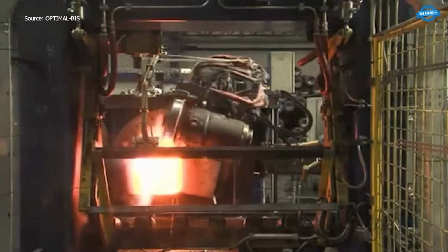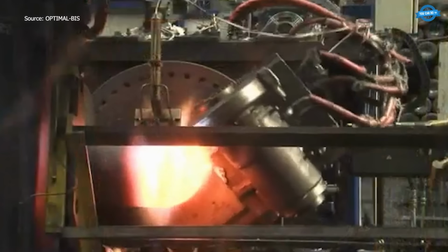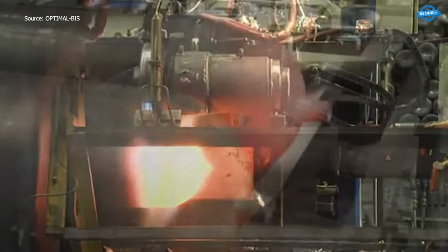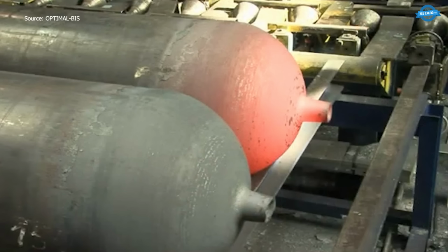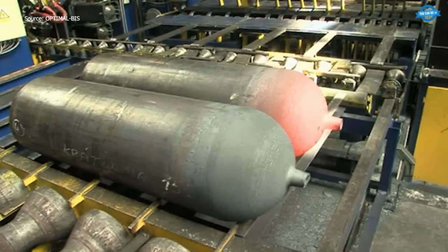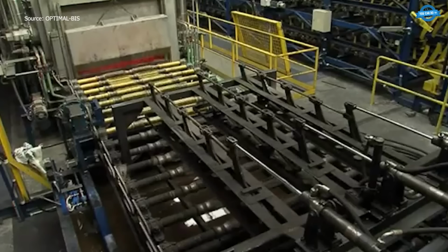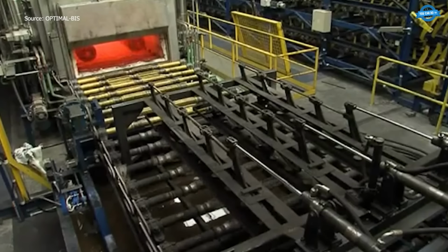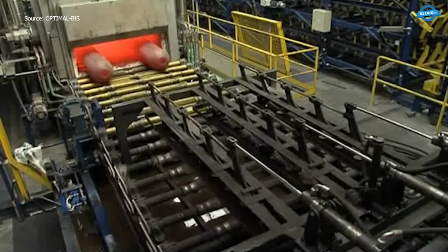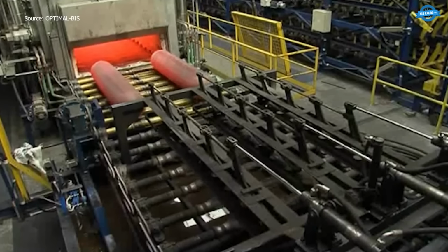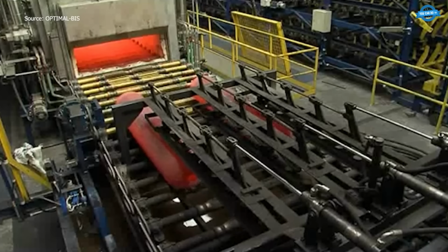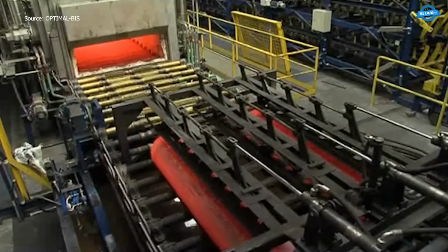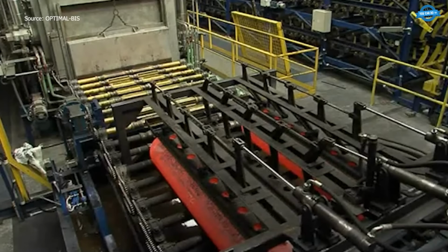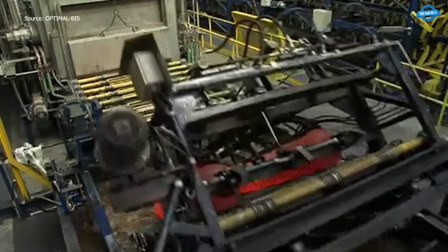After shaping, cylinders go through heat treatment, hardening and tempering to enhance mechanical properties, including impact resistance and strength under extreme pressure. Temperature and timing are strictly controlled to optimize steel microstructure. The hardening process gives the steel a toughness that is remarkable under testing. The next step is final machining. Threads are cut on the neck for valves or O-rings, and both internal and external surfaces are cleaned using shot blasting or chemical cleaning to remove oxides and impurities. Ultrasonic inspection detects any internal flaws.